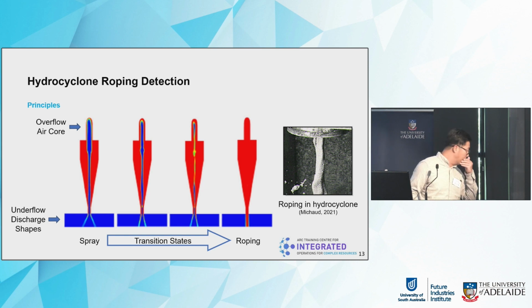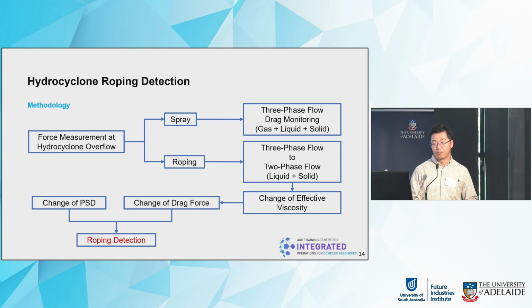So on the left-hand side, it shows the transition from spray to roping of the hydrocyclone working status. One difference is that if we look at the underflow discharge angle, when the roping happens, the angle decreases. And the other difference is that the overflow air core will disappear when the roping happens. So based on this, we got our method to detect the roping by using our force transducer.